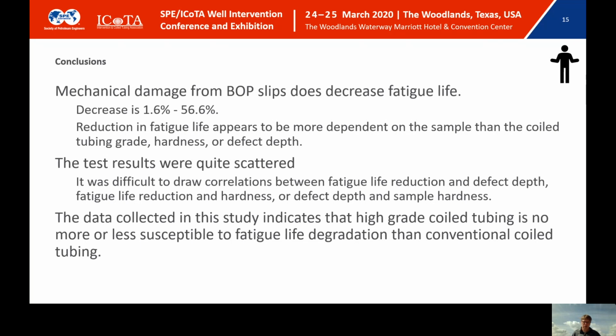And just bear in mind that it's not just setting the slips on the pipe. That would have been less damaging than what we did. We set the slips and then we pulled 100,000 pounds of yield in. So we got a stress concentrator right where the slips are as well.